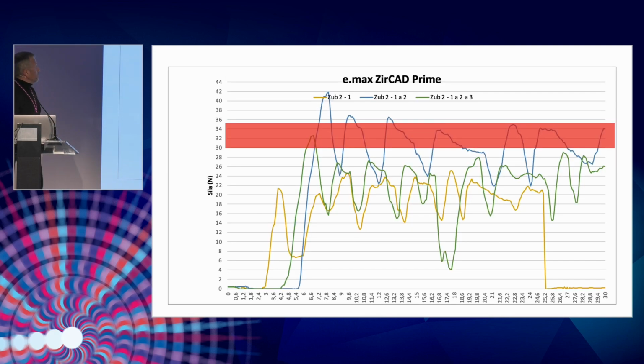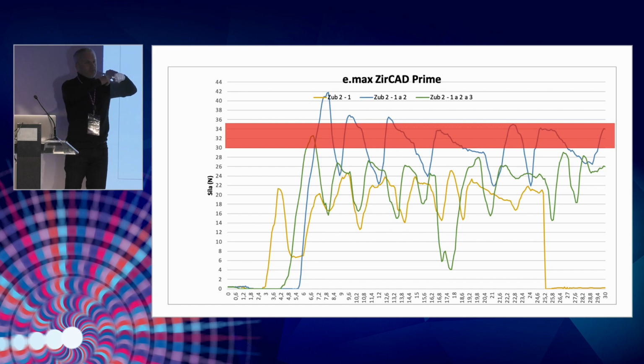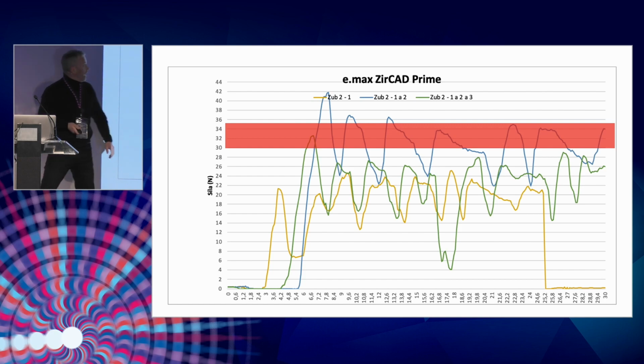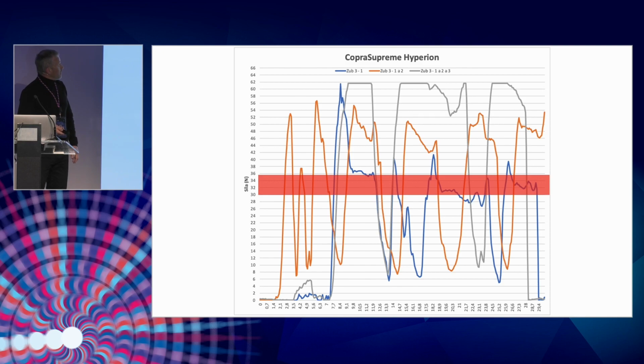Look at the Emax Zircad Prime. It's 42. It's between part 1 and part 2, between the first and second abutment. And Supreme from White Peak, you can see that was more than 60, because the device for measurement was maximum 60 Newton centimeters. That means we don't know how much was in reality, but it was over double the power which we can use for screwing the frameworks.